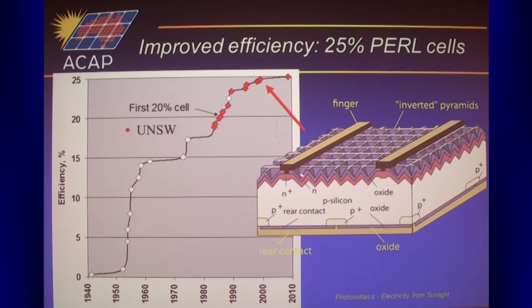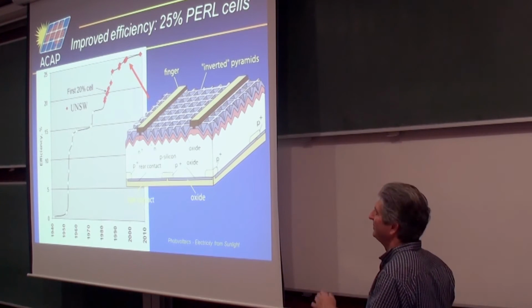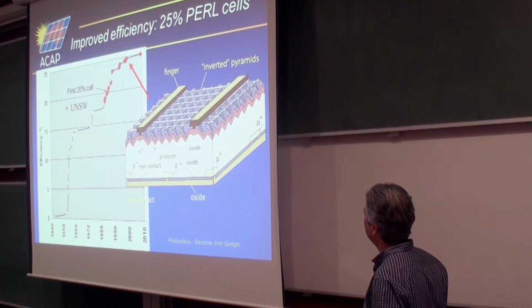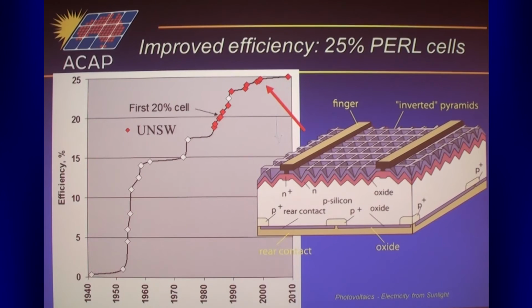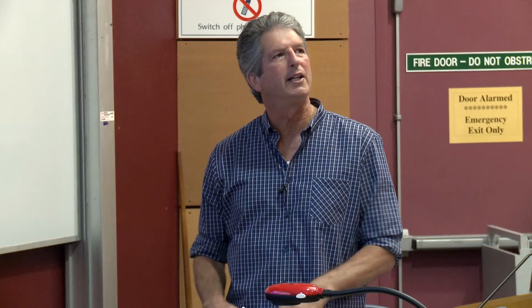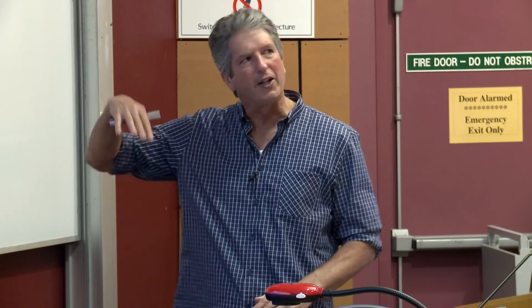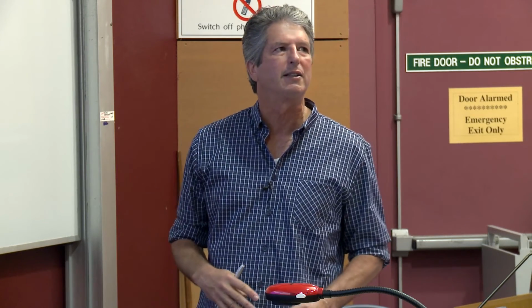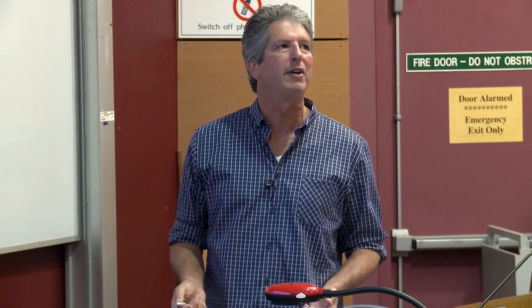Wherever we made contact to the device, we took one extra step. We did a heavy diffusion, which was what was used in the Stanford structure. Oh gee, I'm going to run out of time. So you remember, this is P-type, this is P+. The electron concentration has to be lower in the P+ compared to the P. But the product in thermal equilibrium, the np product, is constant. So this p being high means n has to be low. So what doping in the contact region does, it suppresses the carrier concentration in that region, suppresses the minority carriers, and so that's going to suppress all those gradients to the contact. So that's a way of reducing the contact recombination.